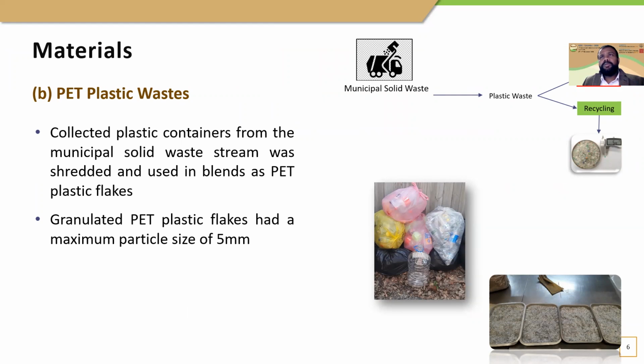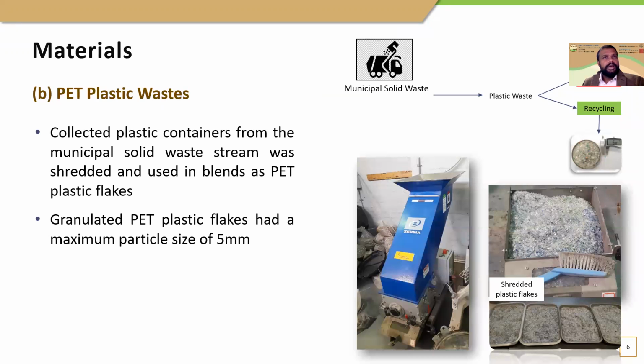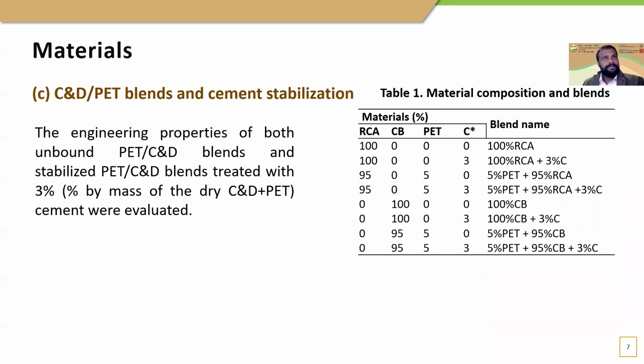Here, the soft drink PET bottles usually have a polypropylene cap, bottleneck ring, and plastic labels assembled around them using adhesives. The plastic containers were washed, dried and shredded into 5 mm particles using a Zerma granulator. And this is the granulator, and these are the shredded plastic flakes of 5 mm particles. And these are the blends which are used in this research. As an example, here 5% PET, 95% RCA, and a third blend with 0% PET. All the percentages are calculated using the dry mass of the materials.